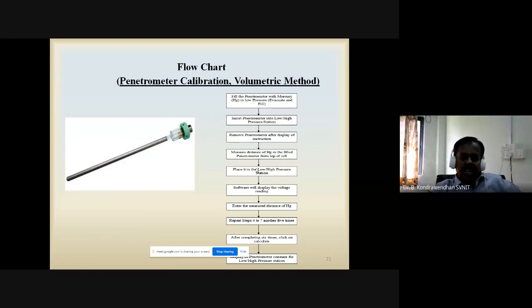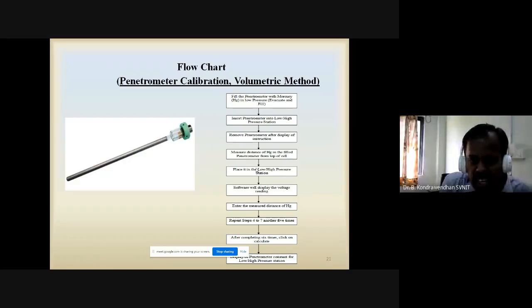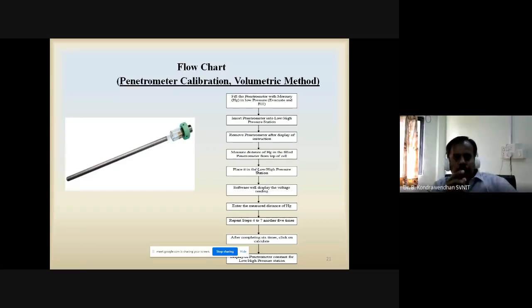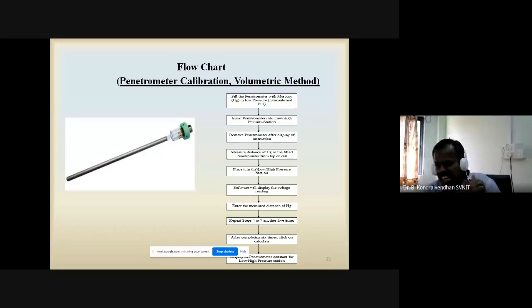Before starting this experiment, one has to determine the penetrometer constant. This is the penetrometer cell. Actually, it is a glass cell only, but it is very sensitive because it can bear pressure up to 60,000 psi. While handling this glass cell, you should be very careful because each cell costs around 20,000 rupees, and sometimes we are dealing with hydraulic oil also. There is a lot of chance it may spill, or it may fall down from your hand. Then it is a bit difficult for you.